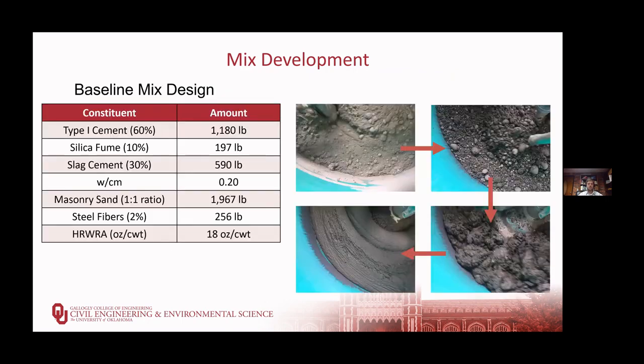That resulted in a baseline mix design that consisted of type 1 cement with 10% silica fume and 30% slag cement by total weight of cement. So we had a high percentage of slag within our mix to replace some of that very expensive cement. We had a water cement ratio of about 0.2. We had masonry sand at a 1-to-1 ratio with our cementitious materials. And then our baseline mix had 2% steel fibers by volume and high range water reducer in the amount of about 18 ounces per 100 pounds of cement.